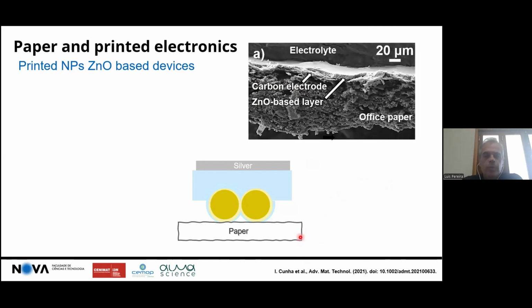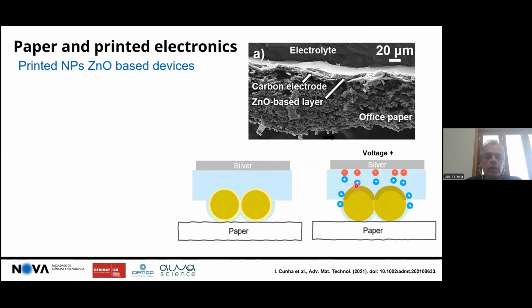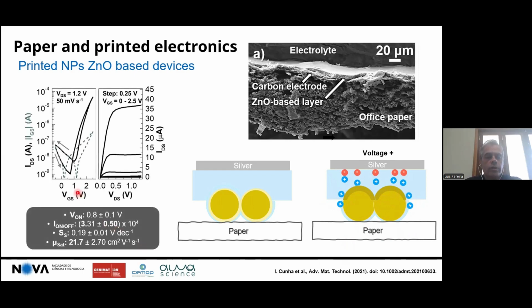And so you see here the office paper with the particles now printed, and on top we have the dielectric. I put here the silver gate electrode. You saw before that this is not indeed the architecture of the device, but I put the gate here just to show what happens when you put a voltage on the gate. So basically you push positive ions from the gate to the surface of the nanoparticles, and you are changing the depletion layer that exists on the surface of the particles resulting from the defects, and you are creating a conductive path around the surface of the particles. One advantage of using electrolytes is that you can get a better coverage also around the surface of the particles, so not relying only on the contact between the particles and the dielectric. And so this nicely results also in devices operating at very low voltages with on-off ratios very convenient and mobilities around 20 square centimeters per volt per second.